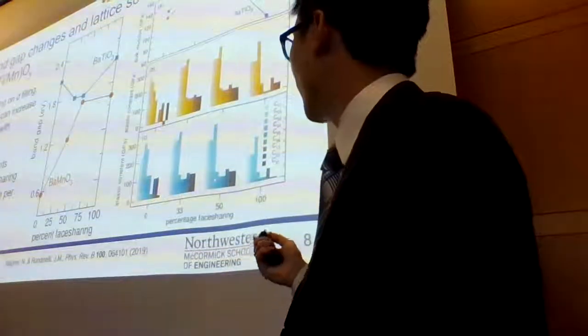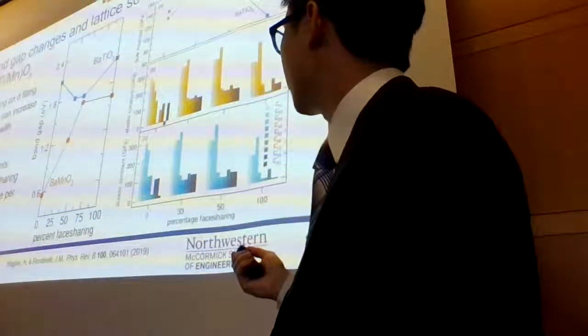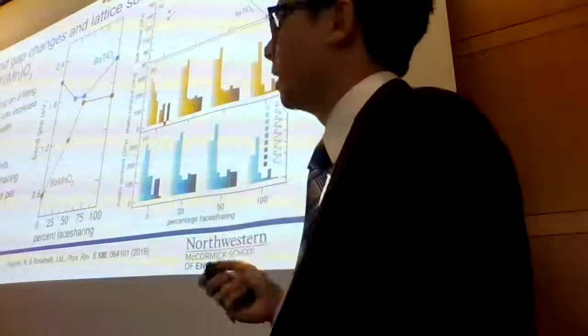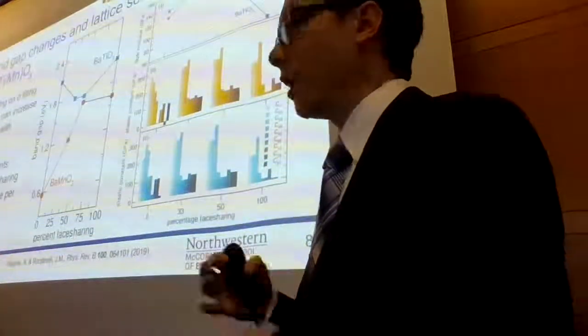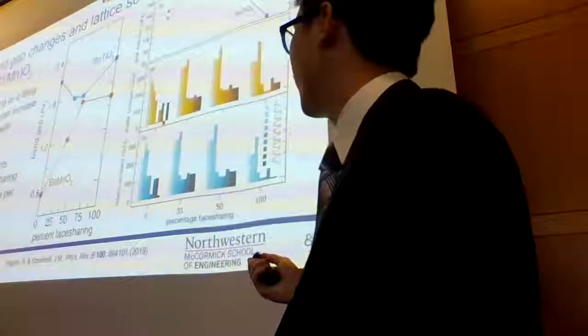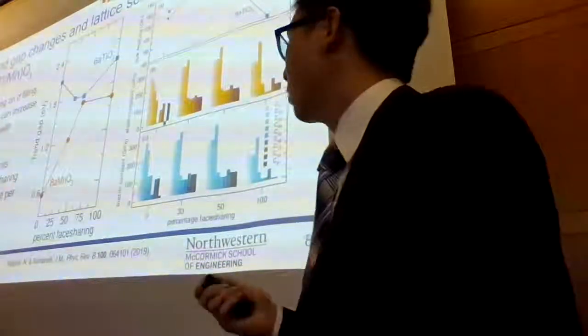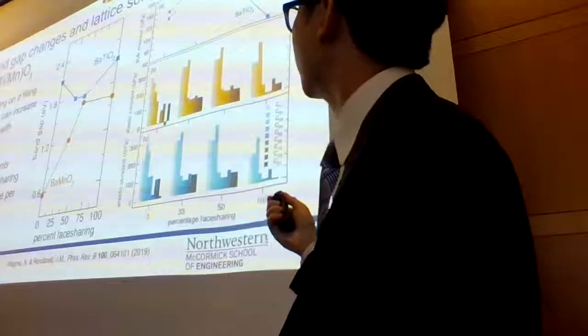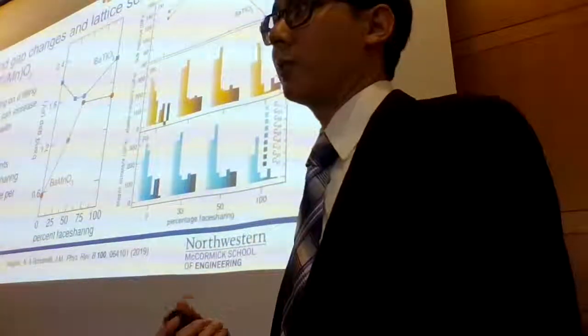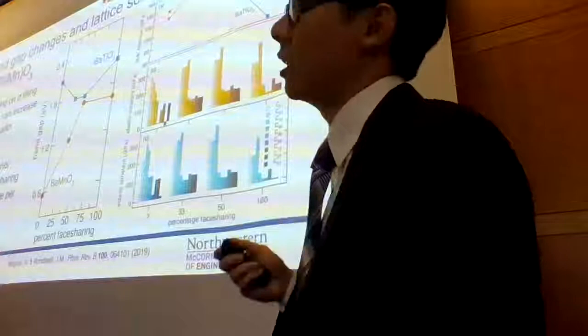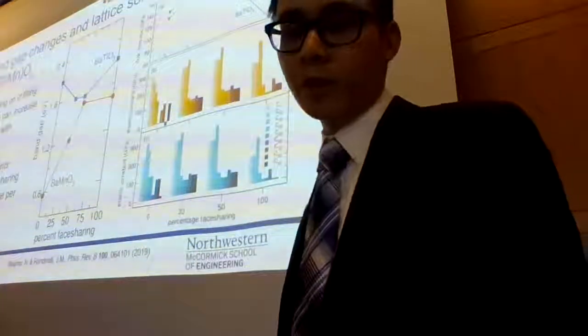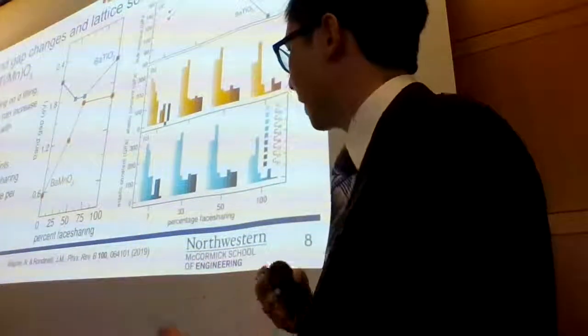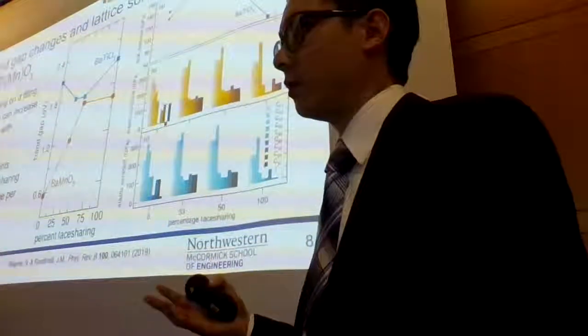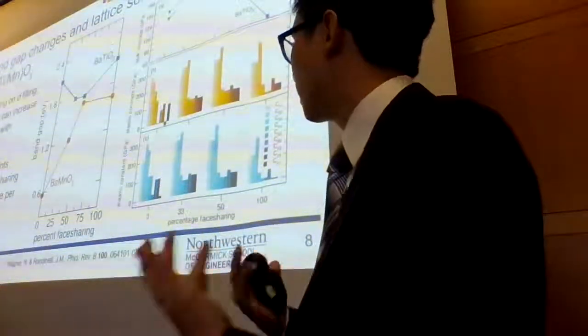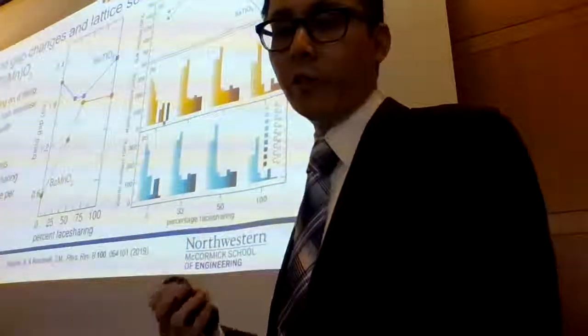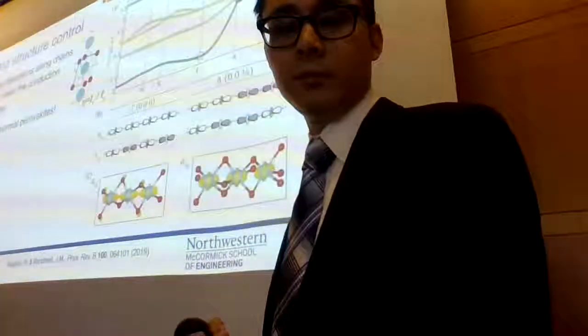But actually, we observed that, if you look at these from left to right, these first two are in-plane elastic constants, and the third one is out of plane. So while along the chain is indeed the strongest direction, overall the elastic constants all soften, and you observe a very sharp decrease in bulk modulus. And again, the cusp is due to polar structures being softer than nonpolar structures. So we can see that this parameter, which we can think about tuning potentially through different synthesis techniques, gives us another knob for engineering the properties in these materials.